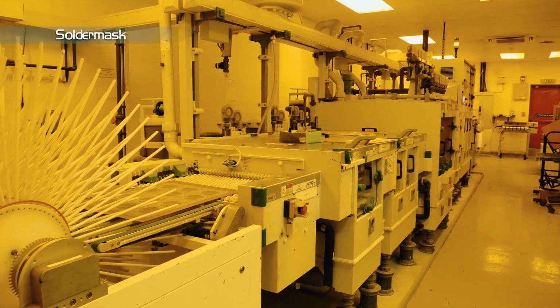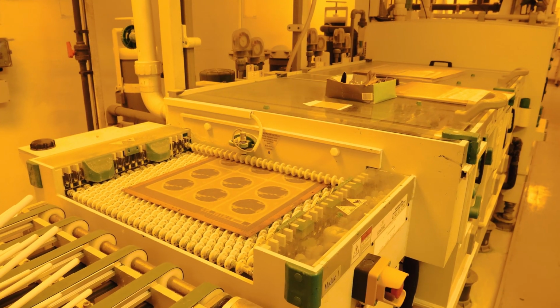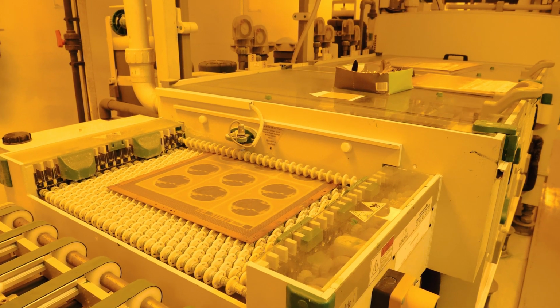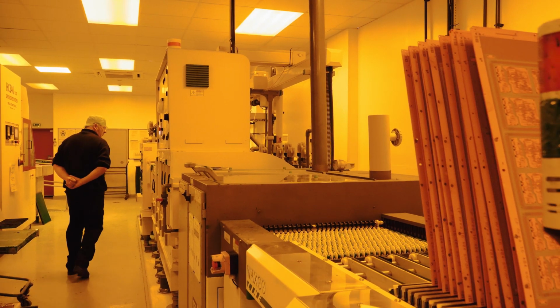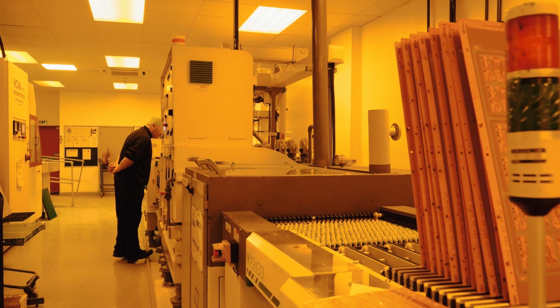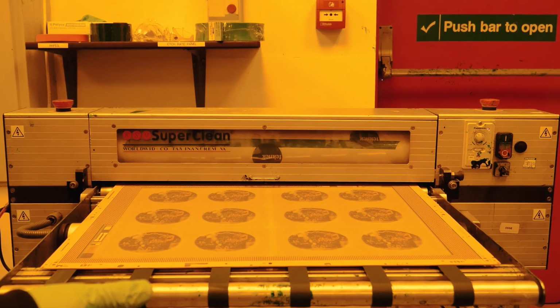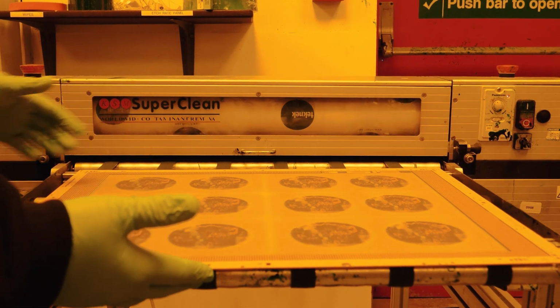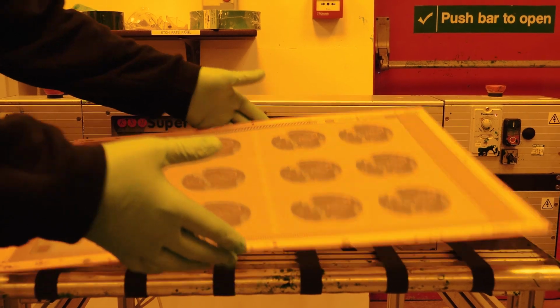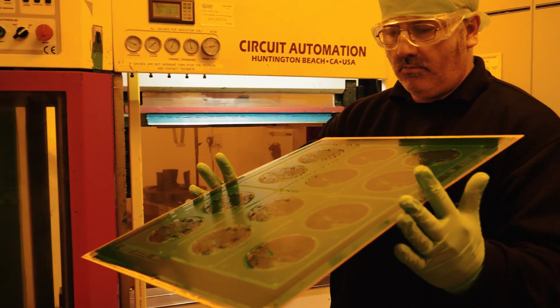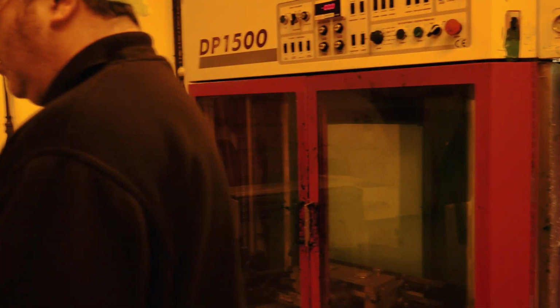The etched panels finally need to have the copper surface roughened, which is done chemically through the MEC etch line. Once the panels have been through the line, they are run through a Teknek roller to remove any FOD. The entire panel is then coated in solder mask using either a spray or screen print process and dried in a tunnel oven.